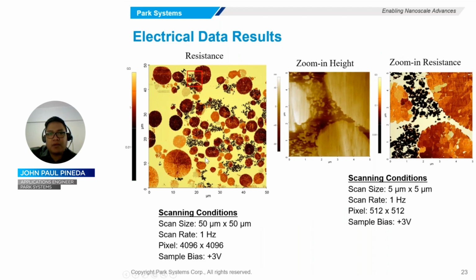So to have a better look at the sample features, a zoom-in view was performed. On the zoom-in image, you can clearly see the small particles which are speculated to be the conductive carbon, while the circular plateaus are speculated to be the lithium metal oxide or active materials. And the low-lying areas here are the areas with the highest resistance, or the high resistance regions.